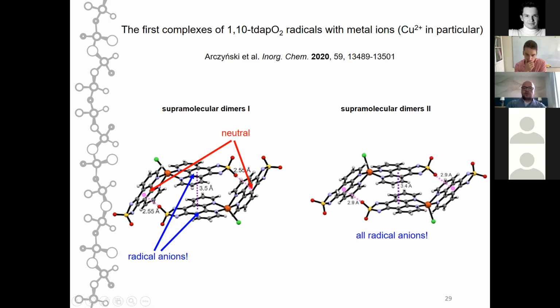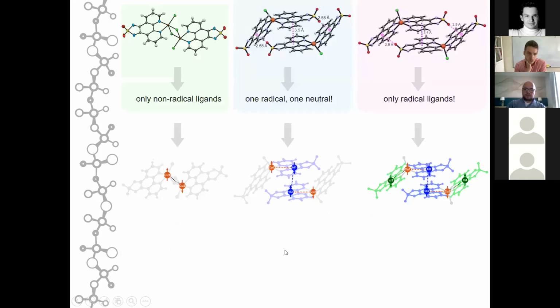This becomes a little bit longer when these side molecules also become anions, but this actually shows that these supramolecular dimers, which are already 2-, are still very robust, and they hold together thanks to these weak interactions. I mean, interactions that are usually considered weak, but in this case, they are strong enough to keep these two molecules close together in this kind of supramolecular dimer conformation.